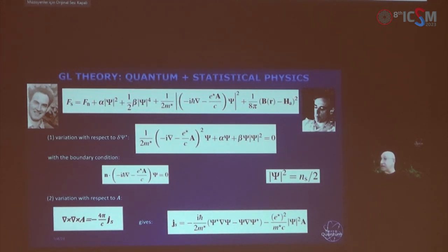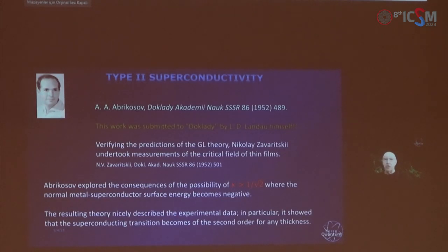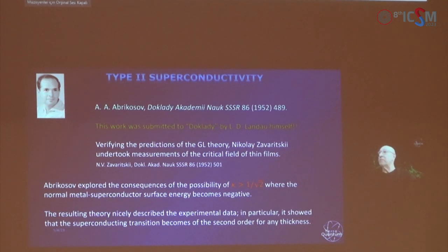And they identified, basically, the amplitude of the order parameter with the density of superconducting electrons at zero temperature. The next outstanding step was made by Abrikosov, who solved the Ginzburg-Landau equation and tried to explain Shubnikov's experiment on the mixed state, a concept that didn't exist at the time, in type 2 superconductors. He explored the possibility of having negative energy at the boundary between superconductor and normal state, and he immediately described the experimental data.